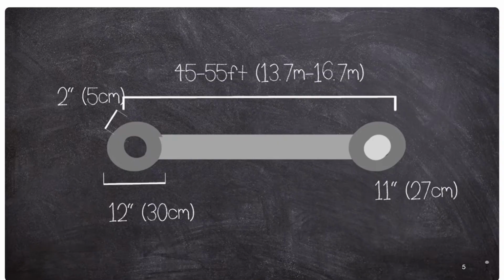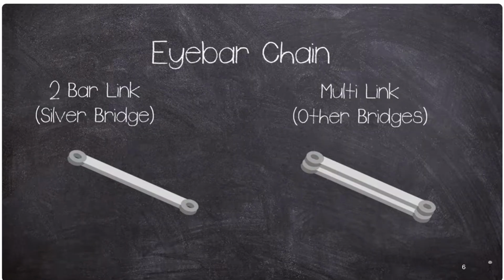The innovative heat-treated carbon steel eye bars used in the Silver Bridge represented a significant advancement for the era. These were long, flat bars, approximately 2 inches by 12 inches wide, 45 to 55 feet long, made from medium to high carbon steel, commonly identified as equivalent to SAE AISI 1060, around 0.60% carbon content. The steel was heat treated, quenched and tempered, to achieve a high tensile strength, typically an ultimate tensile strength of about 105,000 psi, yield strength around 75,000 psi, and allowable working stress of 50,000 psi, allowing